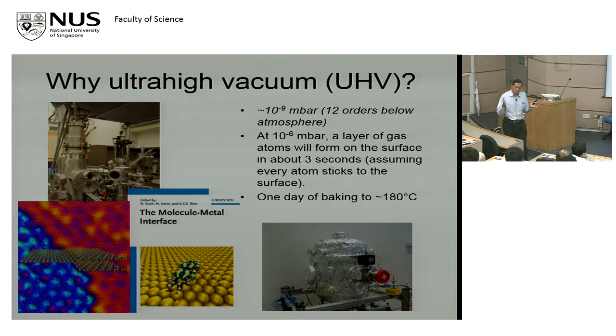And they slowly come off the surface through time. And that's what causes all the residual pressure. But if you bake it, it all comes off more quickly. And then when you cool it down, the pressure drops. Okay, you know that because when you heat a bottle and then you close it up and cool it down, it becomes a vacuum inside. So we are accelerating the process.